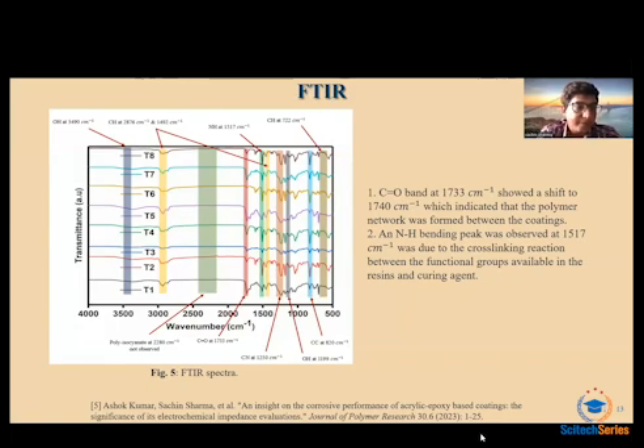Secondly, we can see that after 3,500 per centimeter, there was no band, which indicated that all the curing agents had actually blended well with the matrix, and it did not affect the polymer matrix or the coatings. And finally, the NH bending peak was observed at approximately 1517 per centimeter, and this band was attributed to the cross-linking reactions that had occurred between the functional groups that were available in the curing agent as well as the resin. So figure 5 illustrates the FTIR spectra. And of course, there are other peaks as well.